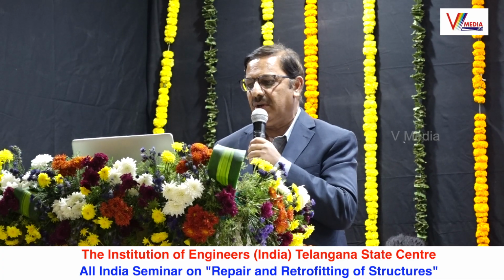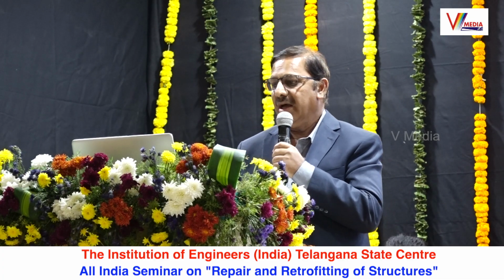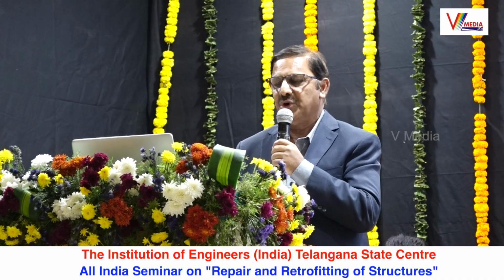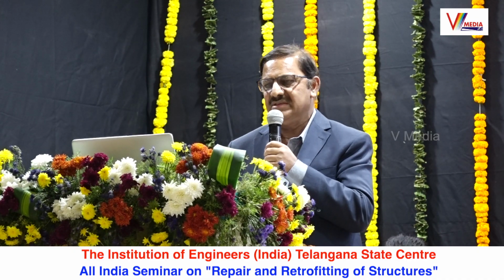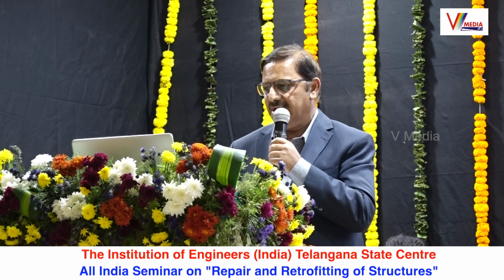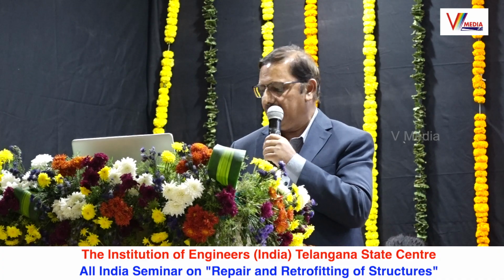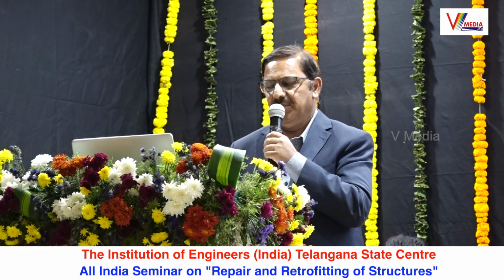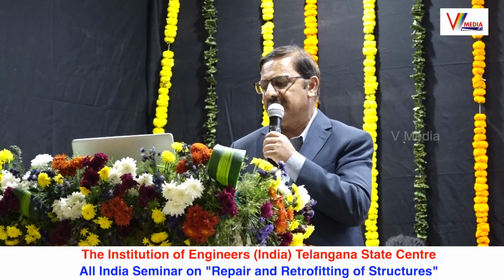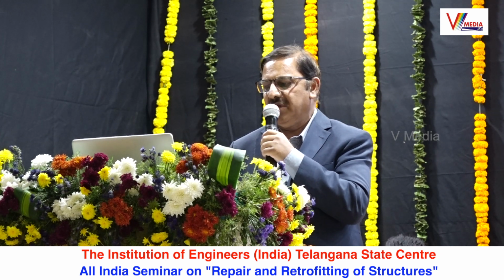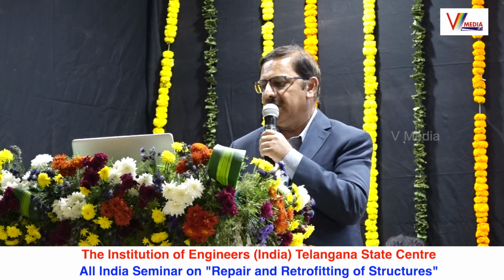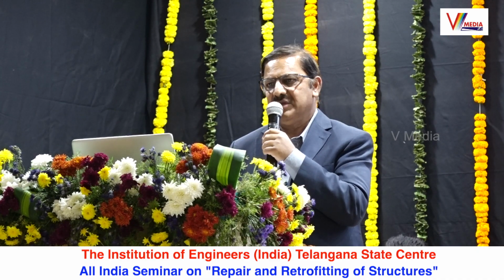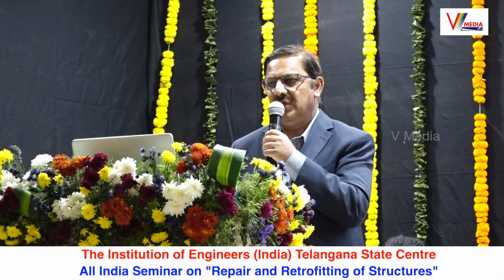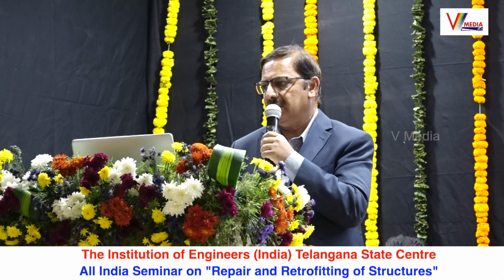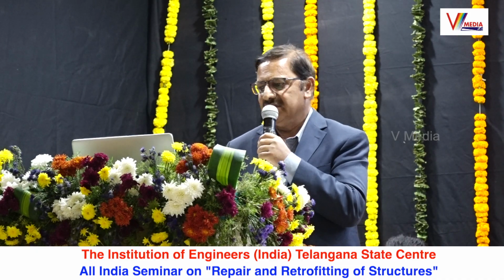In addition to that, if your structure is exposed to an aggressive environment, you need additional protection. This is not required by the codes but is given as a recommendation. It can be a surface coating, which has a limitation. Every technique has a limitation. It has 10 to 12 years of life. Then there are fusion bonded epoxy coated rebars. Avoiding damage to the coating is a very big challenge. To my knowledge, I have not seen any coated steel used without damage. They repair the damage, of course, but the quality of the repair will not be as good as the fusion bonding.